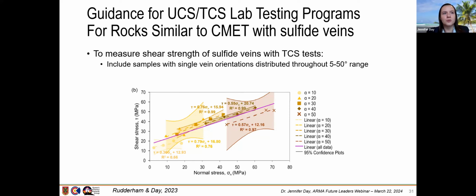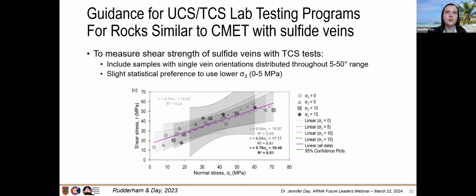You can see in the normal stress versus shear stress plot below, where alpha is the angle of the vein orientation, each vein orientation would give you a smaller section piece of that failure envelope. And so by combining multiple orientations, you would get data along a wider normal stress range. There is a slight statistical preference, based on the confidence interval curves, to use a lower confining stress, between 0 to 5 MPa, as opposed to necessarily saying you need a full distribution from 0 to 15 MPa confinement.